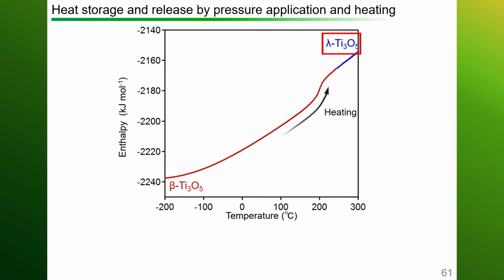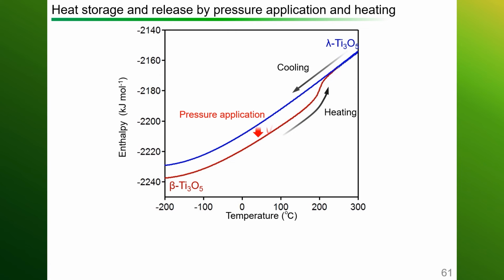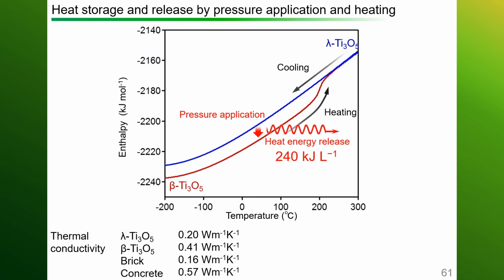The beta Ti3O5, you warm it up to 190 degrees, it makes a phase transition to lambda, and it remains in the lambda state when it's cooled down. So, only when pressure is applied, it releases this much heat, the difference here. The conductivity is like this, like sensible heat storage materials in powder form, and when it cools down, it's like bricks and concrete, sensible heat storage materials.